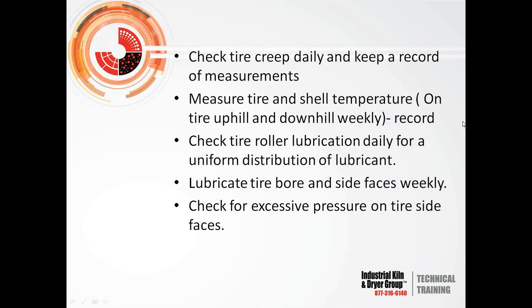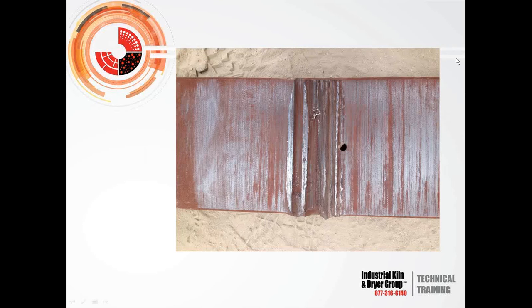Okay. All right. So why don't you give us a rundown on what we should be doing to check this and assist with the tire? Well, essentially, if it was my kiln, I'd check the creep every day. I'd measure at the same time, measure tire temperatures, shell temperatures, and check the graphite blocks, pull them out. If they're glazed, just take a wire brush and clean off the glaze and put them back in. Make sure they're applying graphite to the tire. Usually if you see a shiny tire, you're not getting lubrication. If you see a dull look, you're getting decent lubrication. It should be uniform.